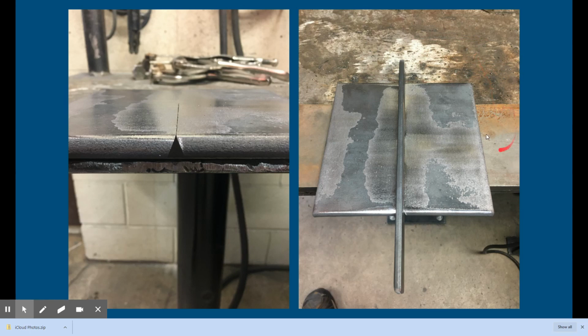So I always have the students put it on a flat piece of cold rolled. We've just got a few lying around. They'll set that on top of their table as a nice flat surface. The WPS calls for a 1/4-inch root opening. So all we do is take our backing strip, and we just stand it up on edge. Our backing strip is a 1/4 inch by 1 inch. So you can see I get my bevels. This happens to be the 3G weld. I'll get my bevels set up so they're just perfectly flush with each other.